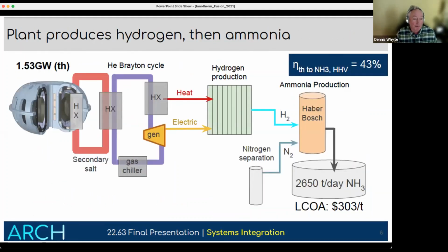It ended up taking some real thinking, and it almost all came down to heat transfer. This is why I think it's germane to the colloquium. So we took an ARC class device, and in the end, this made about 1.5 gigawatts thermal. That was feasible within the design. Then we set up heat exchange into a secondary salt, helium Brayton cycle. We used some of the heat to generate some electricity, and for the hydrogen production, we used the Haber-Bosch process, taking the molecular hydrogen, separating out the nitrogen. We came up with a target for the power plant of making about 2,600 tons per day of ammonia, and we got very close to our economic target, at around $300 per ton, with the efficiency you see up on the top here.